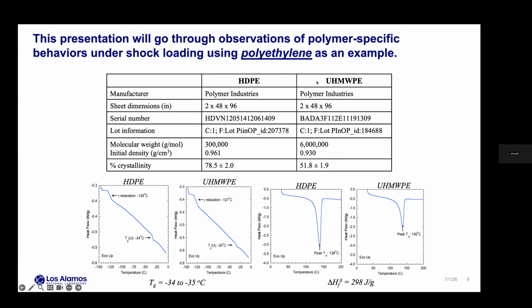The other type of polyethylene is ultra-high molecular weight polyethylene. That has found a lot of uses in armor and protection and protective equipment because it tends to have some texture associated with it, and the high molecular weight inhibits crystallization. So we're typically at around 50% crystalline, and also because of that, we end up having a lower density in the final product. So I just want to introduce you to those two materials.